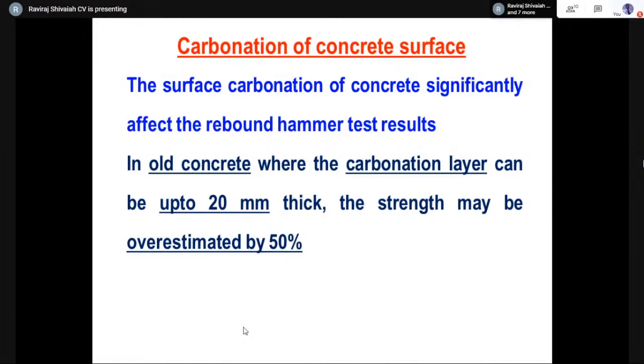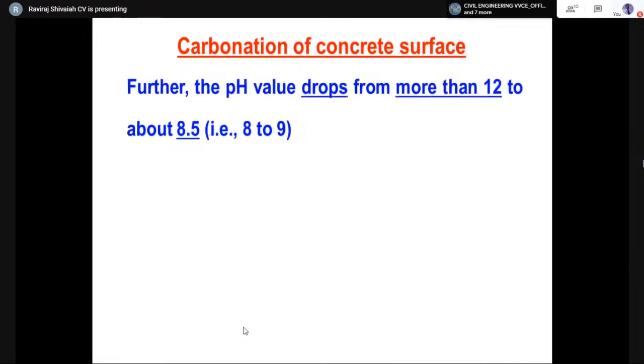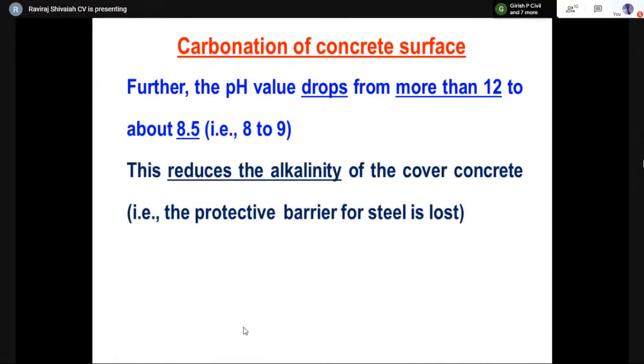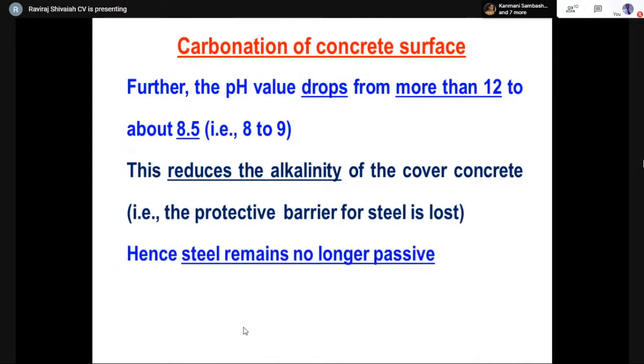And the rebound numbers could be overestimated by 50%, and that may mislead us into saying that the strength of the concrete is good. Please understand, once the carbonation happens, because you're consuming alkaline calcium hydroxide, the pH value also drops, from an average of 12 to something like 8.5. So it has reduced. Once the alkalinity has dropped, the protection barrier of the cover concrete has reduced. And this leads to an exposure of steel for corrosion.